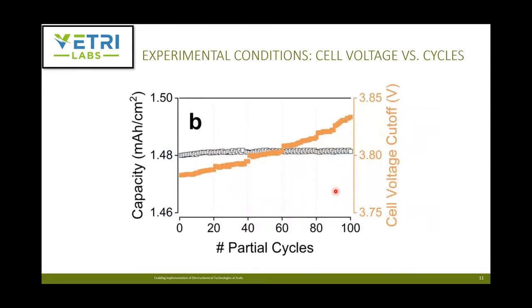The other thing that they did is, instead of using the voltage to determine the state of charge, they used the actual capacity in milliampere hour per square centimeter as the state of charge. What this does is it forces the cell voltage to be higher as a function of your cycles. So you're actually accelerating 2 ways. One, you're accelerating by going to that SOC. Number 2, you're pushing the cathode potential to be high because your cutoff voltage keeps going up with respect to the number of cycles. As a result, there is a double factor influence in the aging condition here.